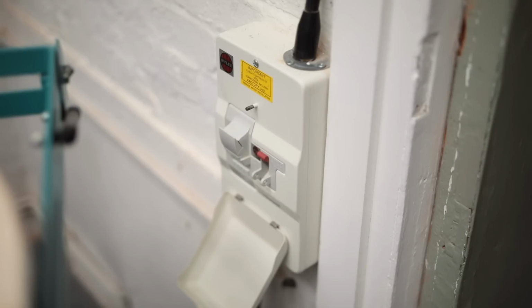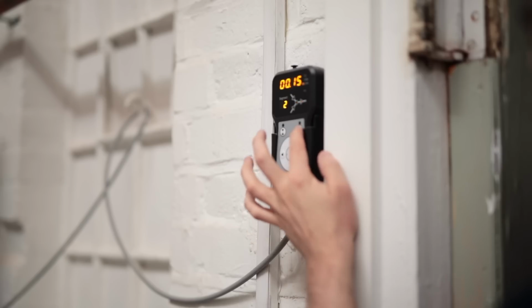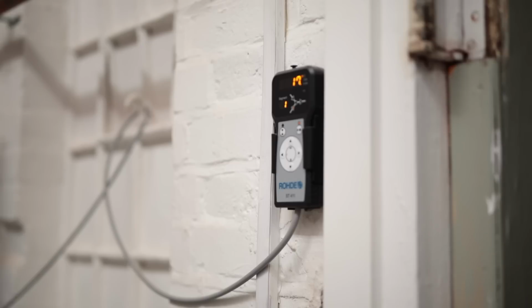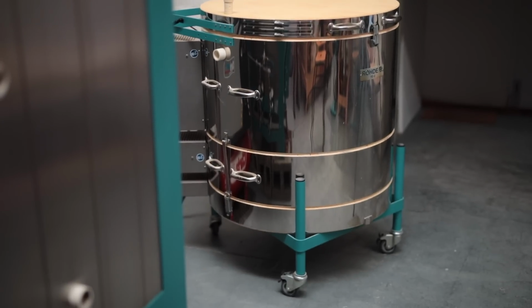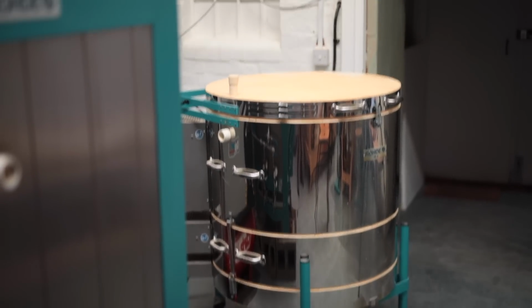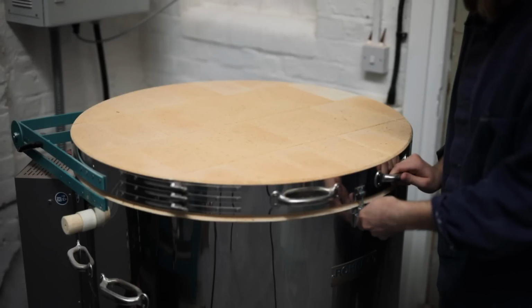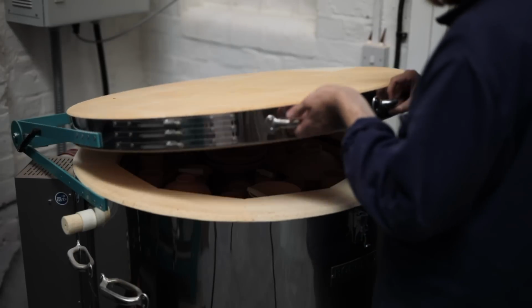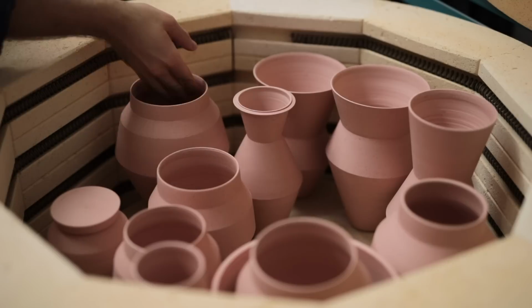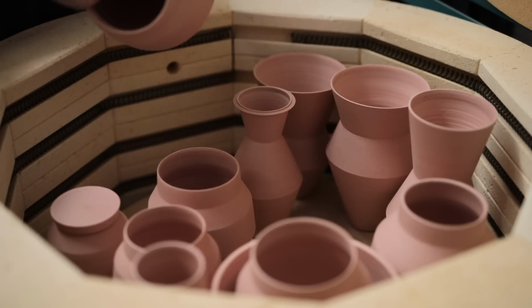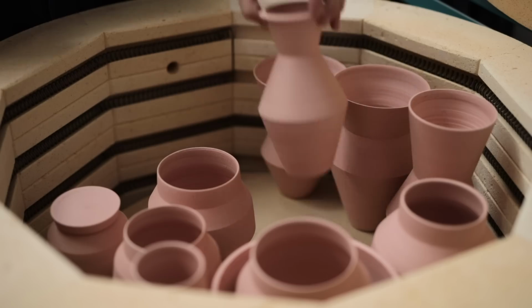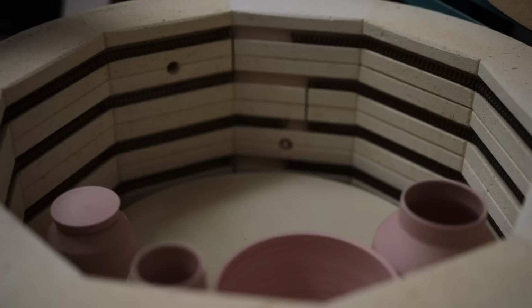The kiln is then switched on and fired overnight to just under 1000 degrees Celsius. This firing causes the clay to undergo an irreversible process, and it changes soft clay into hard ceramic. About a day and a half later, the kiln can be unpacked, and you can see the difference in colour now they've been fired, and also the fact that they've shrunk slightly. In fact, this clay body shrinks about 12% from freshly thrown to finally glaze fired.